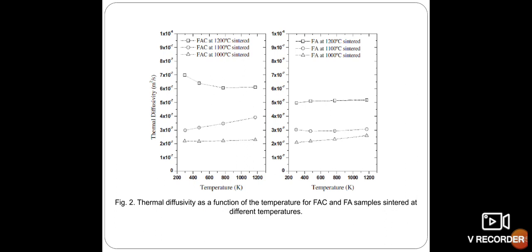Besides, the thermal diffusivity values for FAC and FA are almost temperature independent, and it can be observed that these values are nearly constant in the whole temperature range, varying from 2 × 10^-7 to 7 × 10^-7 square meters per second, and 2 × 10^-7 to 5 × 10^-7 square meters per second for FAC and FA respectively. The FAC samples show slightly higher thermal diffusivity values than the FA samples. The possible reason is related to the air-filled core. Air shows thermal diffusivity values as high as that of the metals, which helps to enhance the diffusivity of FAC samples.